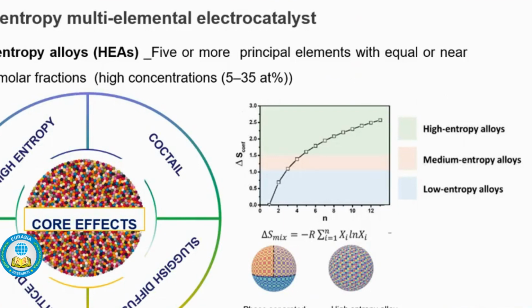High-entropy alloys are a new class of multi-elemental alloys that involve high mixing of 5 or more elements at near equiatomic concentration, and the core effects that differentiate those materials from traditional alloys include high entropy, slow diffusion, lattice distortion, and the cocktail effect. The system of these alloys possesses a high degree of entropy compared to conventional alloys, with advantageous properties such as corrosion resistance, chemical stability, and improved catalytic activity.